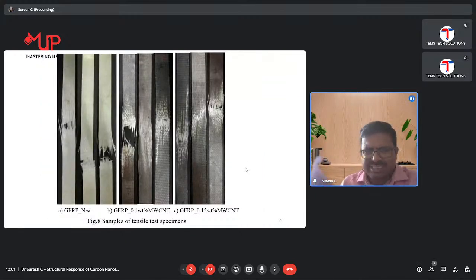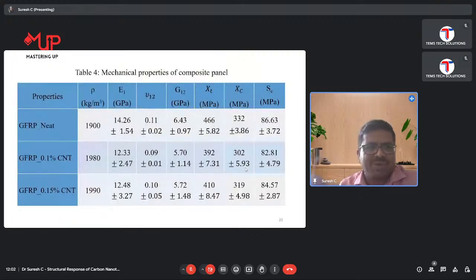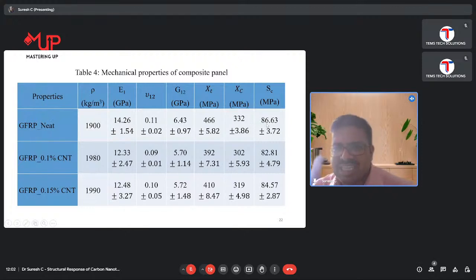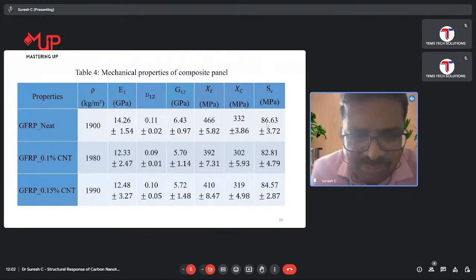So these are all our experimental tests, how the test plate with the different carbon nanotubes behaves. Next, to carry out the numerical simulations, we need to find out the mechanical properties of the carbon composite plates. So we tested in a tensile test and estimated the mechanical properties. We cut the specimen and did the density test by burning the specimens inside a furnace. Before furnace and after furnace, we found the weight, and from the mass and weight we calculated the density. Then Young's modulus, shear modulus, the strength in tensile direction, compression direction, and shear direction, everything we have tested, and we found out the mechanical properties of the composites.